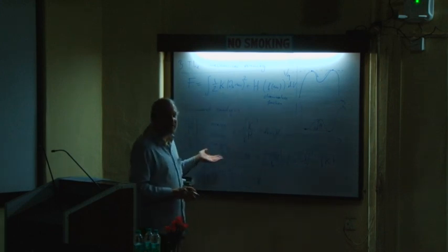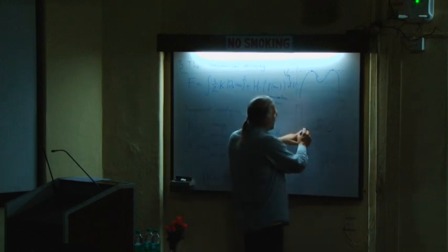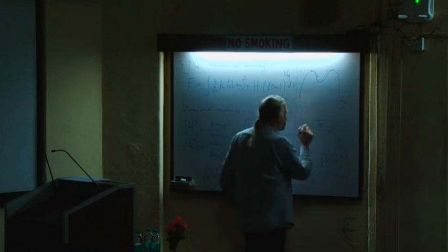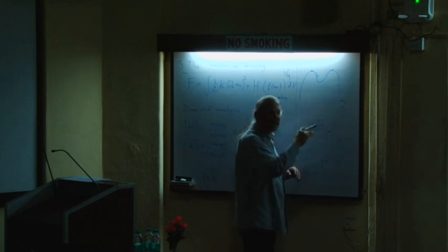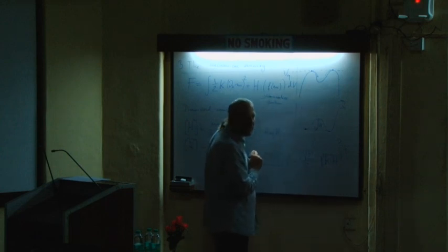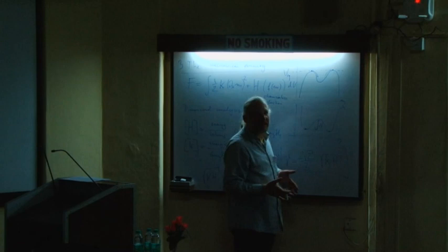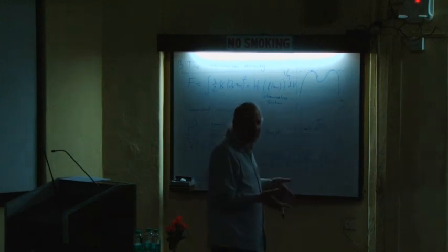It's also very intuitive. As I have said some time ago, if you want to go from one phase to the other, it costs some energy because you have to get over the hill. Now the scale of the energy that you have to invest to get over the hill is given by the constant h, because this is the height of the hill. And this hill will contribute in the interfacial region, and the interfacial region has a width of epsilon.